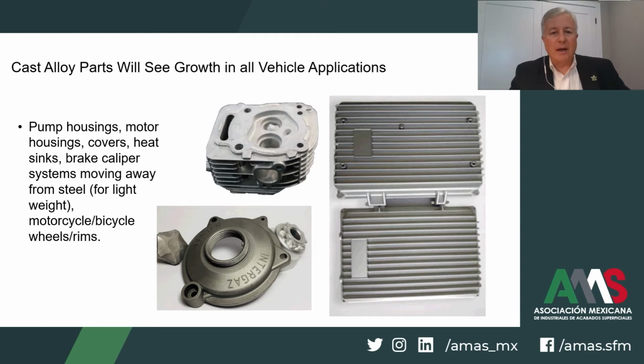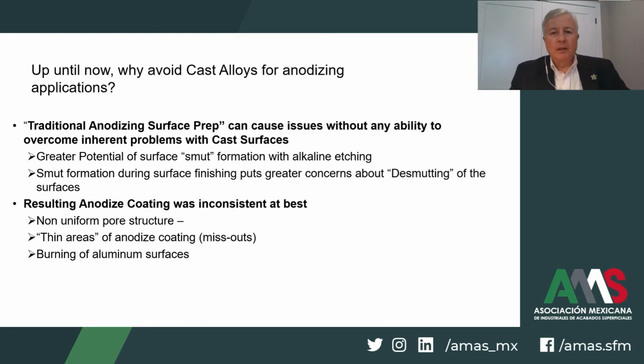As shown in this slide, here are some examples of the types of parts that are currently or that will be constructed from cast aluminum and that will require some very good capability for anodizing successfully with these types of components. Traditionally, we know why cast alloys were being avoided for anodizing processes. They were easily etched, they had the formation of the complex smuts that would result from the wrong processing. Remember, in traditional anodizing, the processing sequences would include alkaline etching, and they would cause complex oxides that would cause smuts, which would cause difficulty for creating the oxide formation on their surfaces.